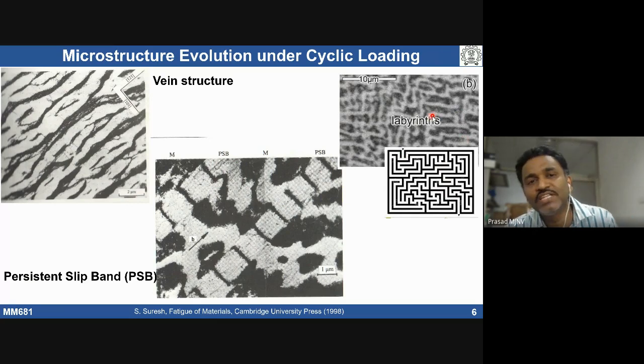So this is the kind of characteristic microstructural feature we see if the material has undergone cyclic plastic deformation. If you see formation of these persistent slip bands in a microstructure at high magnification, we can say that a particular component has undergone cyclic plastic deformation. Is it clear? I think I stopped at this point in my previous lecture. If there are any doubts, please let me know before proceeding further.